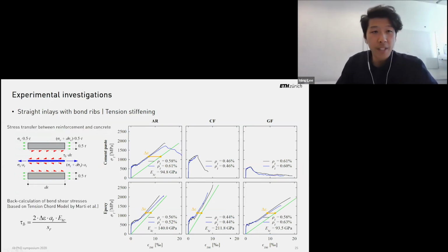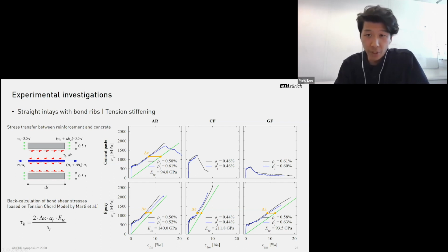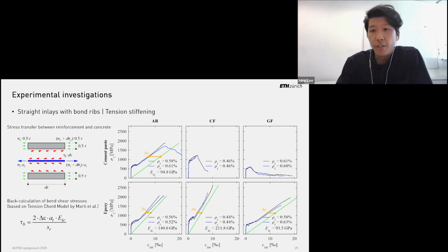So last points to these experiments: in all specimens with hardening behavior, a clear effect of tension stiffening could be observed. That means the mean strains were lower when compared to the bare textile, here denoted as green line, the load deformation plots. And due to the interaction of reinforcement and concrete, part of the load between cracks is taken by the concrete, reducing the strains in the reinforcement. And if we assume a constant bond-slip relationship, the tension chord model developed by Professor Marty can be used, and this leads to the possibility to back-calculate the bond shear stresses with very few parameters.